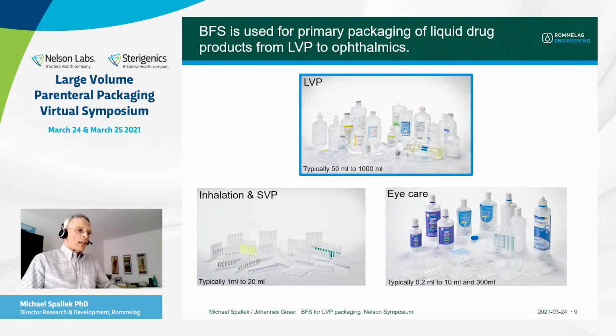What about container designs, container shapes? General blow, fill, and seal can be used for very small containers, as shown here in the eye care section, where we typically have 0.2, even less, milliliter filling volume for these single dose eye drops. In the mid-range, we have the inhalation drug products and the small volume parenterals. These are in the range of typically 1 to 20 ml. And as for today, for the large volume parenterals, we typically have 50 milliliters to 1,000 milliliter filling volume.